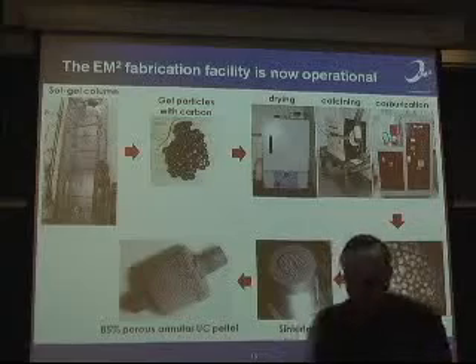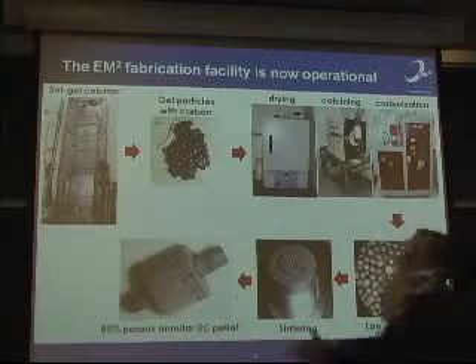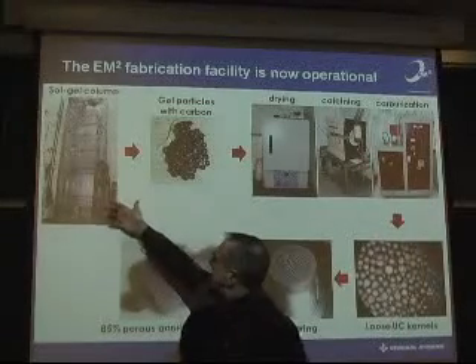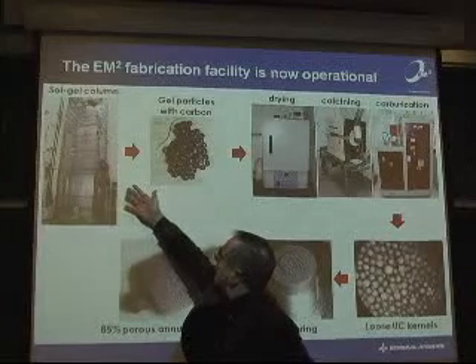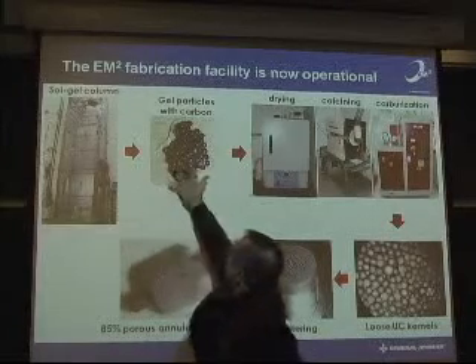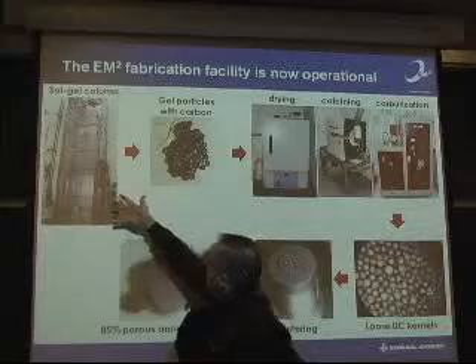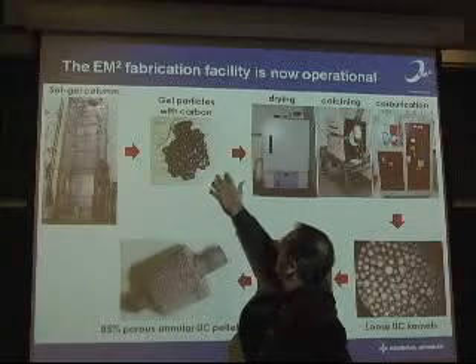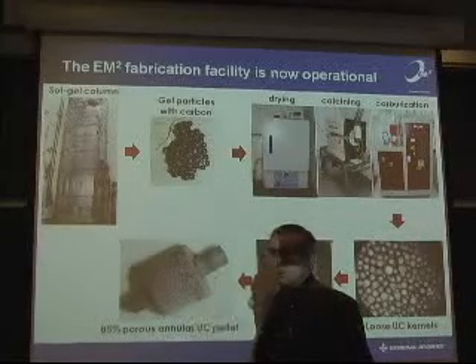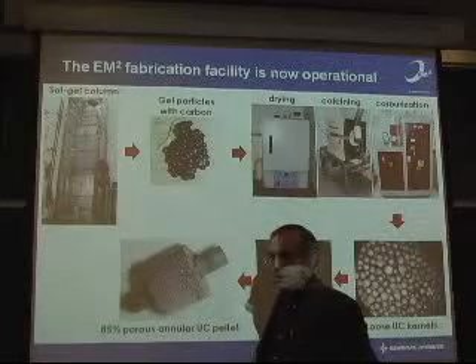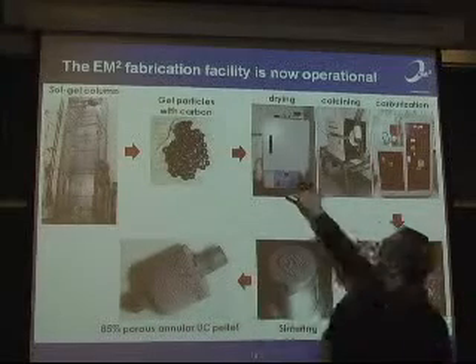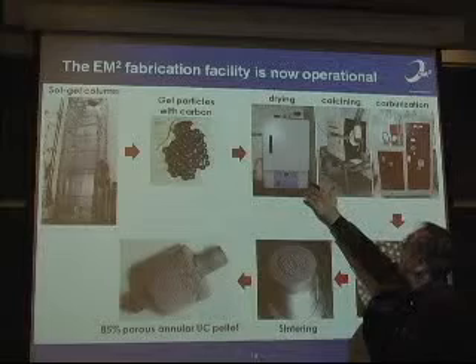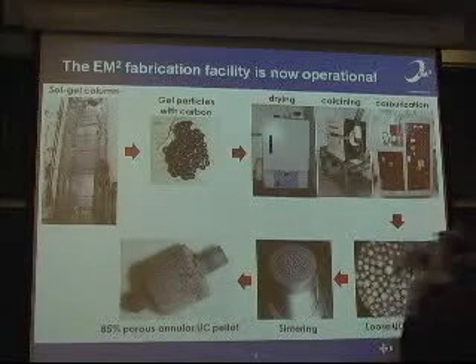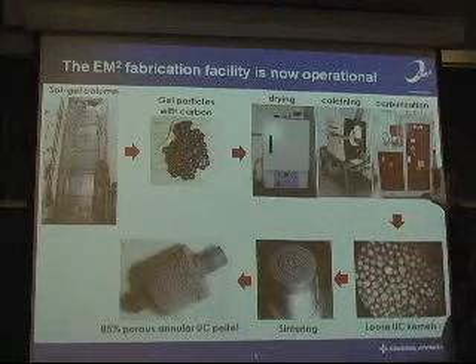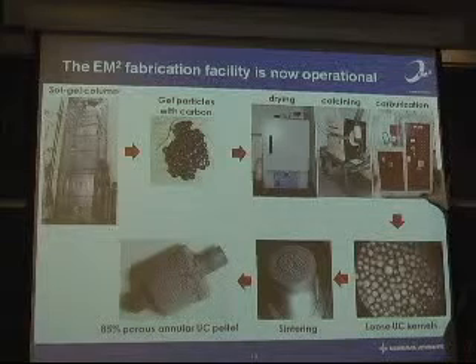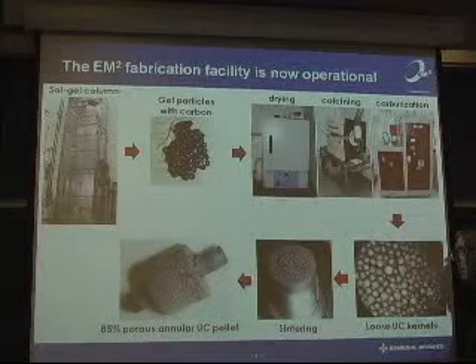And so this shows how we make fuel. We make uranyl nitrate gel particles in the sol gel column there. You can see they're black. We put some secret sauce in there that has carbon material in it. Then you go through a very carefully controlled drying, calcining, and carburization stage. And at this high temperature furnace, then we convert the oxide to monocarbide.